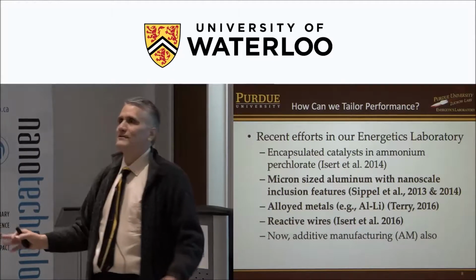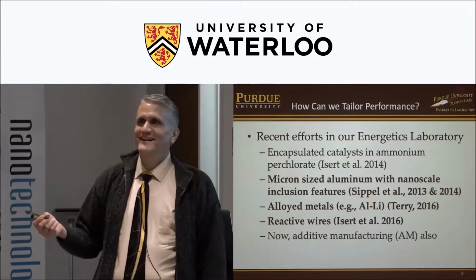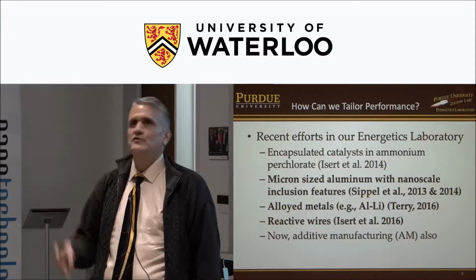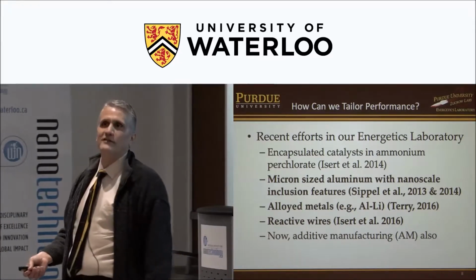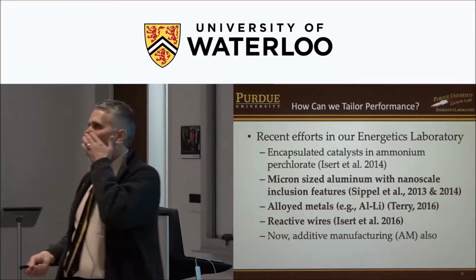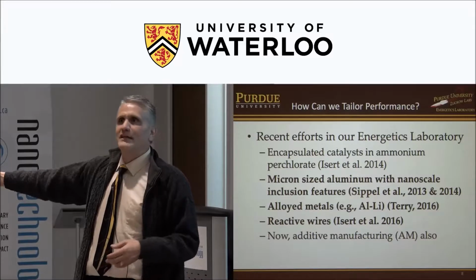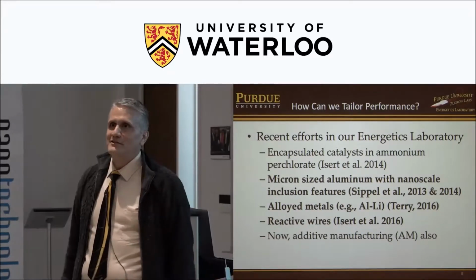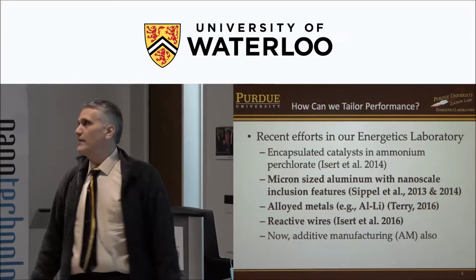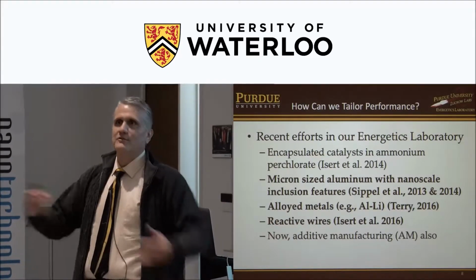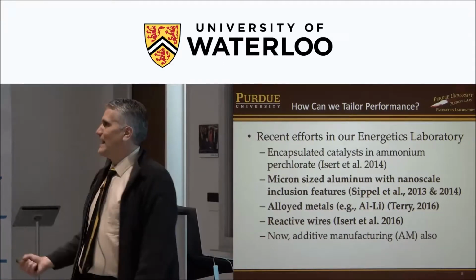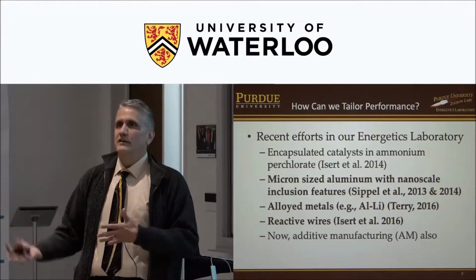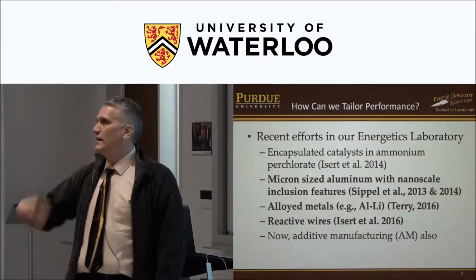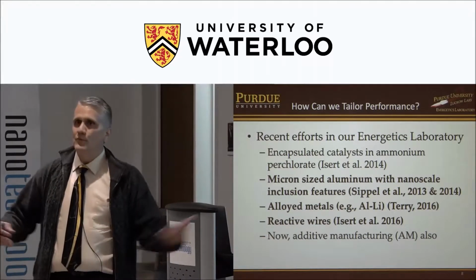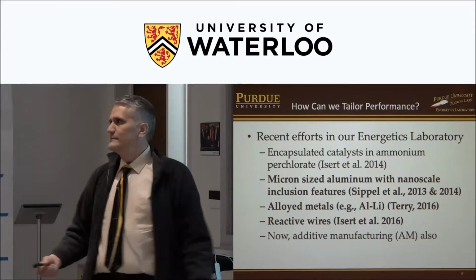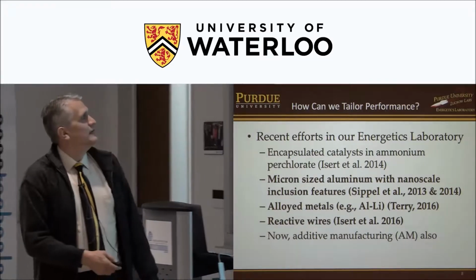Now you're all engineers, so you're like, what the heck is halophilic? Anybody know it? It likes things like halogens. Yeah, that literally means it loves halogens. Halogens like chlorine, ammonium perchlorate. So it has chlorine in there, so the typical solid propellant produces HCl. What do you think HCl does to your launch site and acid rain, all that stuff? Not a great thing, right? It'd be nice to get rid of that, but people have looked at additives and it kills performance. You're cutting the energy. The lithium, being halophilic, forms lithium chloride instead of lithium oxide, and so it ties up that chlorine and you produce hydrogen instead without the HCl. So it's less toxic pollutants and less caustic.